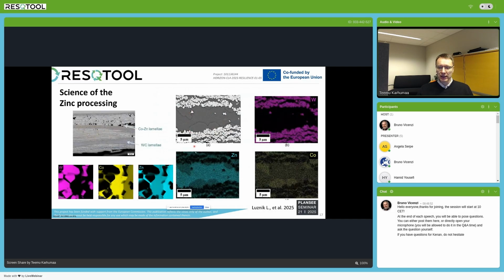And as you see here, for example here in the middle, the zinc-cobalt rich lamella. There are different phases consisting of different amounts of cobalt and zinc. But indeed, the zinc and cobalt both are in between of these tungsten carbide grains.